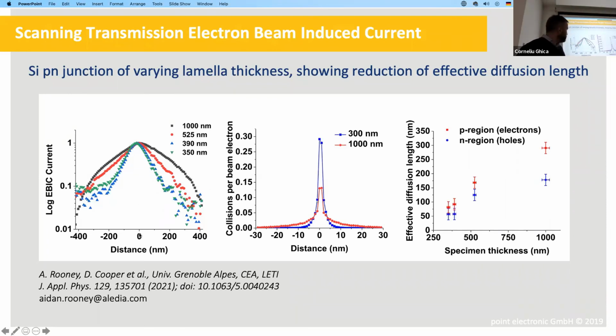But to take that slowly, we see that the edges away from the field go all the way to something like 400 nanometers, so quite far away from the junction. If we compare that with Monte Carlo simulations of how far we expect the electrons to deviate from their path as we go to thicker and thicker materials, we see that, yes, as the materials go thicker, you expect the primary electrons to have more displacement, but this is tens of nanometers, so about 10 times smaller than the diffusion-driven signal that we see here. So we can then apply a standard formula and extract the decay parameter from here. And then we can give with good confidence what the diffusion length of minority carriers is.